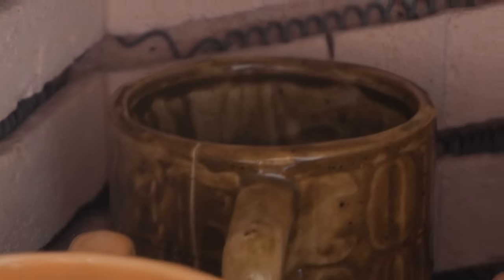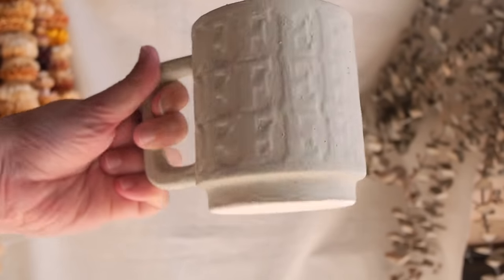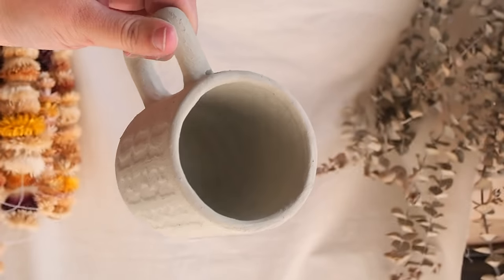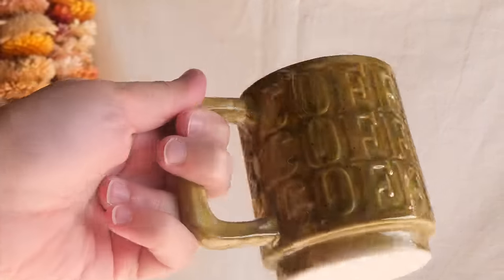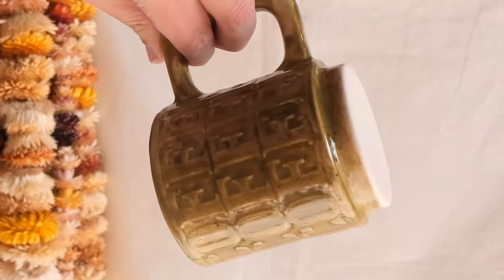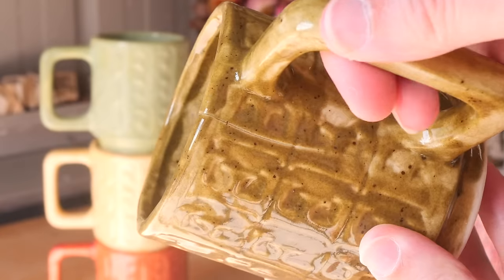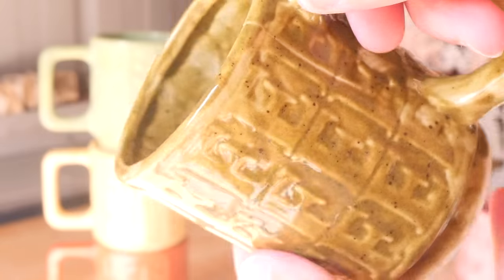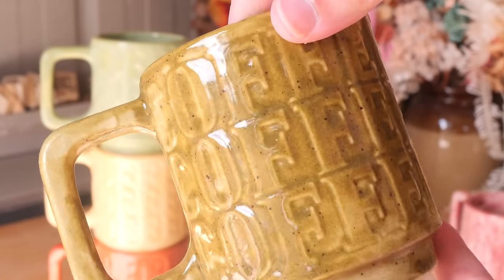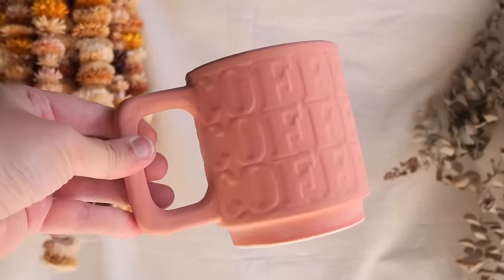I open up the kiln and you can see my face reaction as I looked at the colour and then saw the crack at the back — how much it had blown open. The speckled green glaze looks amazing on this coffee mug, especially tying into the 70s colour palette. But the crack has opened up so much. From a hairline crack it has blown apart; the lip no longer lines up, it goes all the way through, and it's quite a bright white. This would not be usable for drinking — I would use it as a pot or break it down for a mosaic.